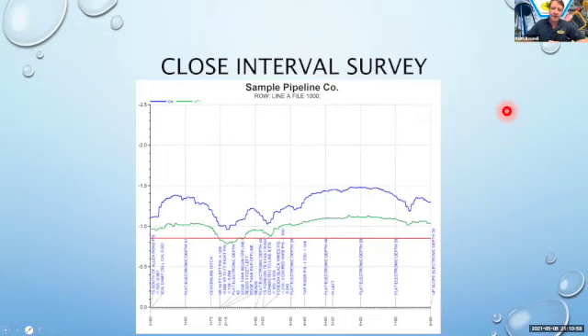In looking at some of the data, there was some close interval survey done back in 2018 by Alyeska. Some of the same concerns I had regarding their annual test point survey, where they had elevated polarized potentials, were seen also in the close interval survey data, where they had polarized potentials of negative 1.5 to negative 1.8 volts, which definitely is some kind of error in that reading. And they did have a small section of polarized potentials that were below 0.85, below criteria, which they've since said they have addressed, but I haven't seen the actual data to confirm or deny whether that's been taken care of.